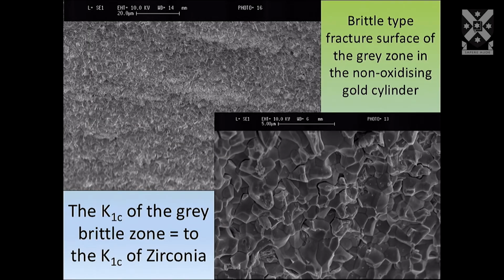And sure enough, the surface topography showed us a brittle mode type failure, so it was brittle as opposed to ductile, as we'd expect to see in a metal. And we found the fracture toughness was the same as that of zirconia. So inadvertently, this soldering process was creating a ceramic-like brittle zone within a ductile metal system. And once a crack reached it, there was a catastrophic failure.